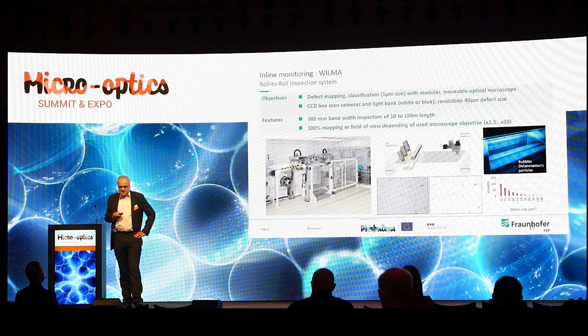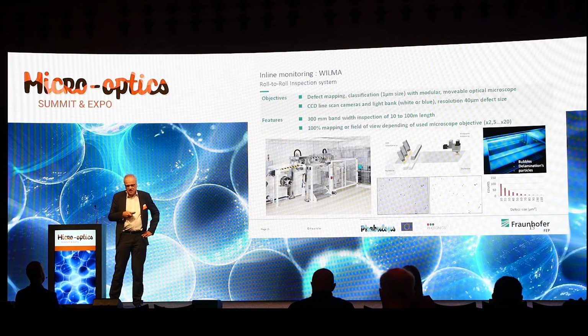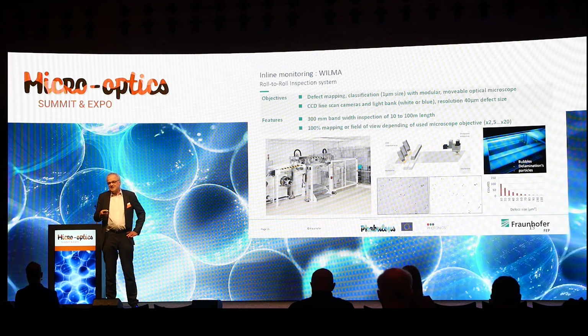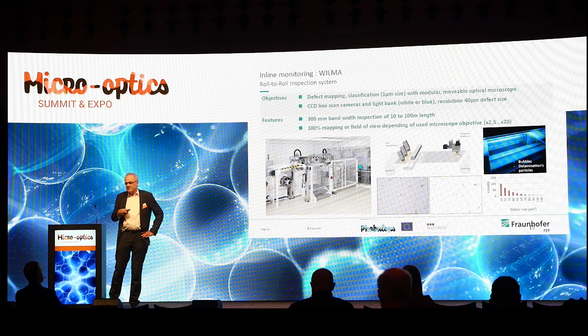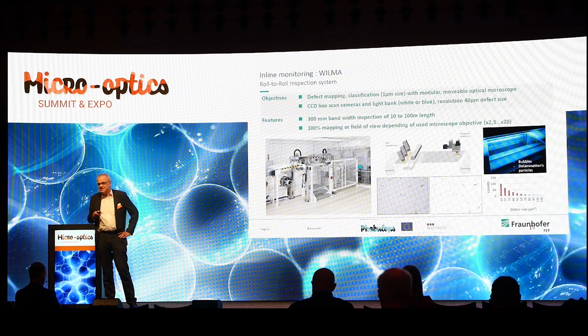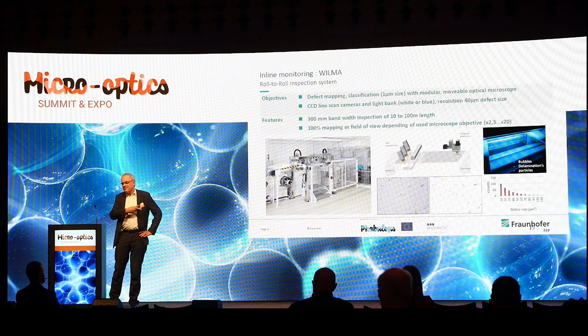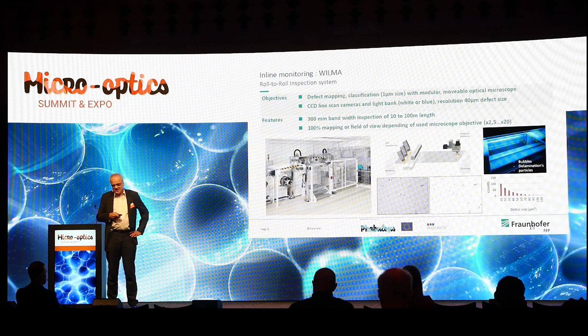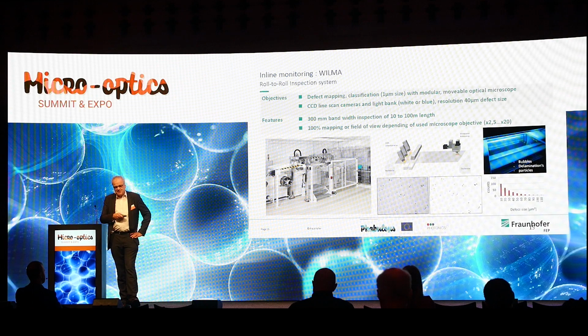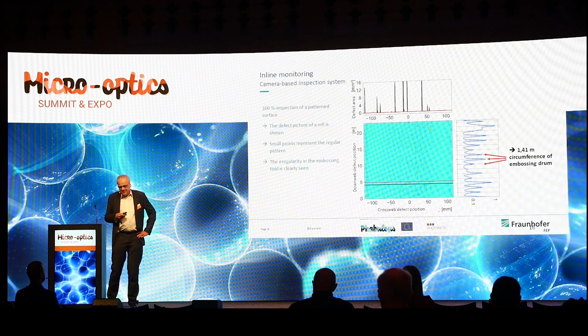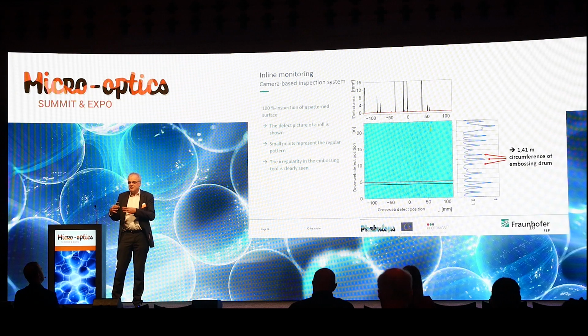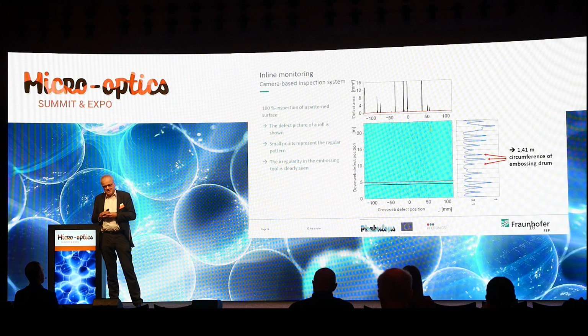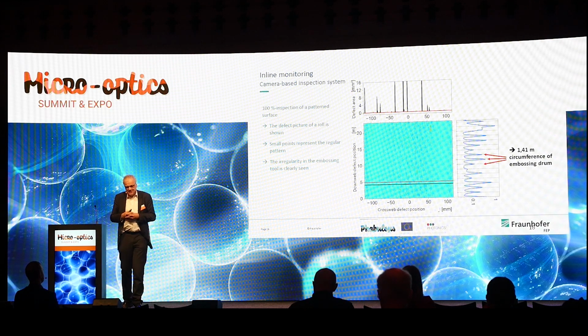So that's why we had this inspection device, and now we tried to use this also for pattern substrates, for substrates which have a microstructure on top of this. So that's not so easy, because every microstructure is primarily for this device a defect. Nevertheless, we could adapt the software in such a way that the device was capable of distinguishing between regular defects and real defects in the structure. And this we could demonstrate quite well in this one, which is shown here.